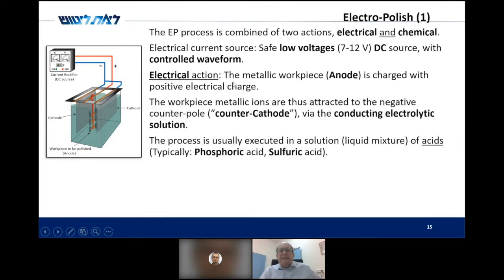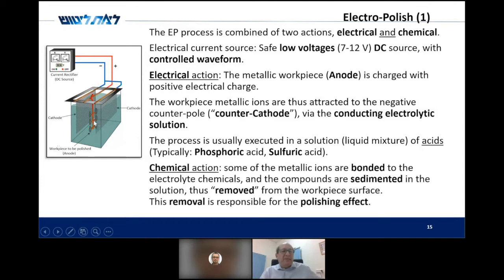The electrical action is that the metallic workpiece, which is connected to the anode, is charged with positive electrical charges, and they are being attracted to the cathodes, the counter cathodes, via the conducting electrolytic solution. And this solution is usually a mixture of several acids, some weak acids like phosphoric, and some strong acids like sulfuric. This is an electric action, but it is combined with chemical action. Some of these metallic ions that leave the workpiece towards the cathode are bonded to the electrolyte chemicals, and the compounds are sedimented in the solution and removed from the surface of the workpiece, and this removal is the polishing effect.